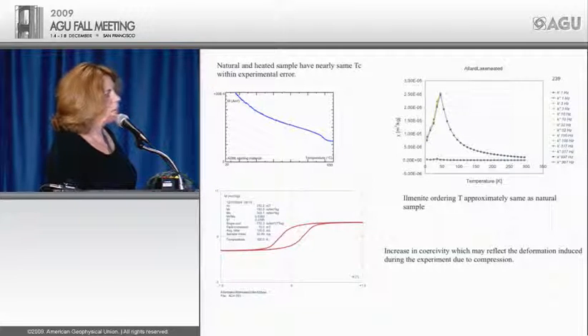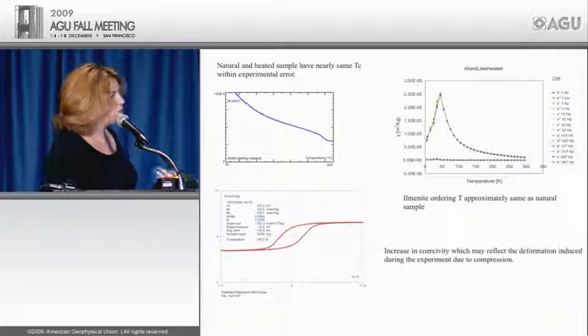I think basically what we found is we probably were near the conditions where the Allard Lake was crystallizing. It probably was around 10 kilobars. But this certainly tells us that this mineralogy is stable.